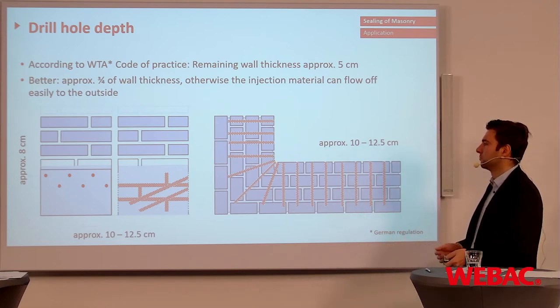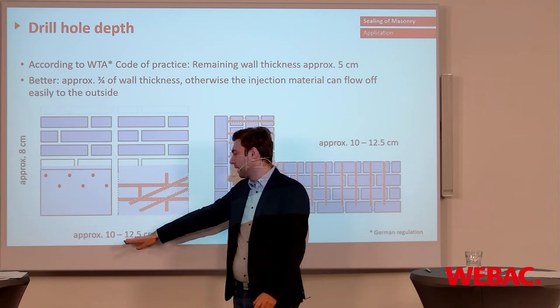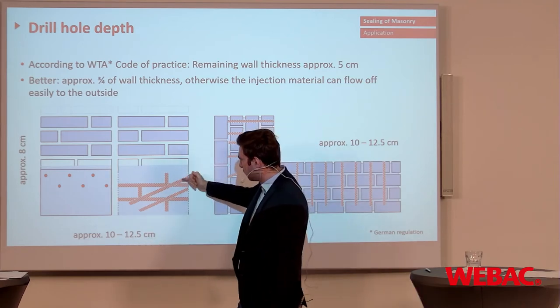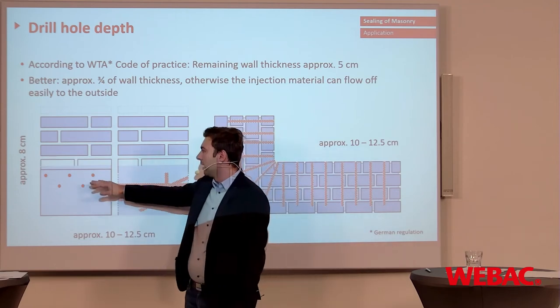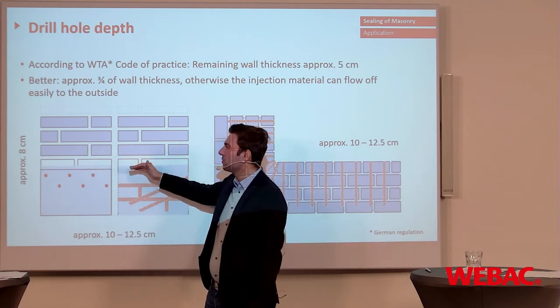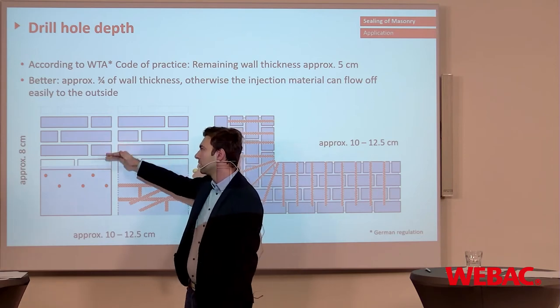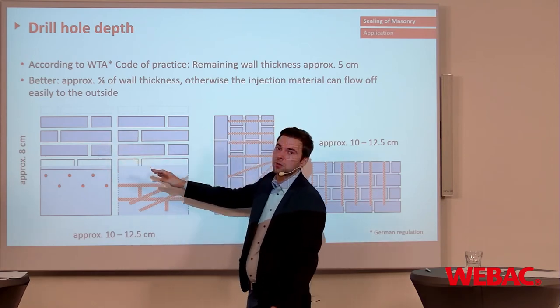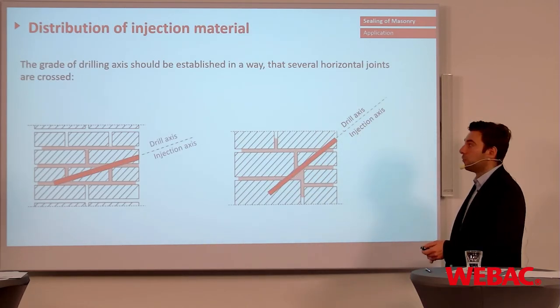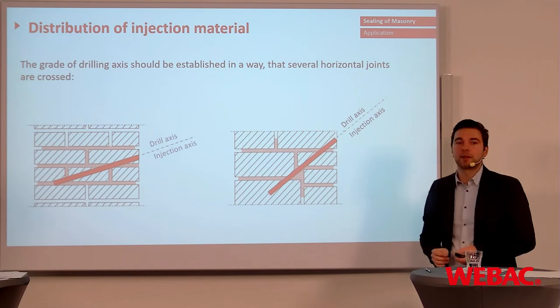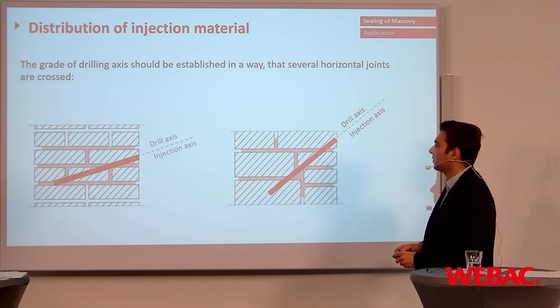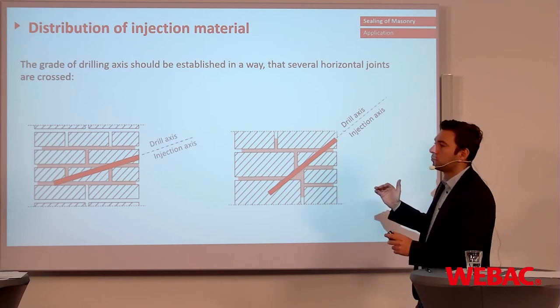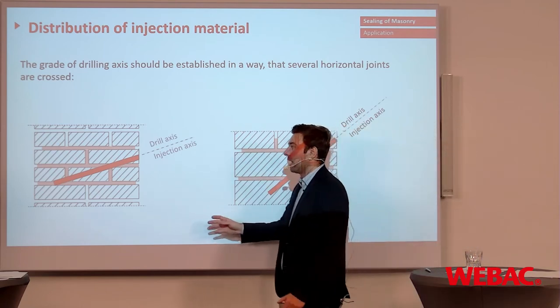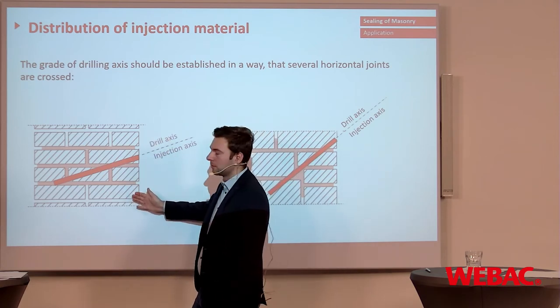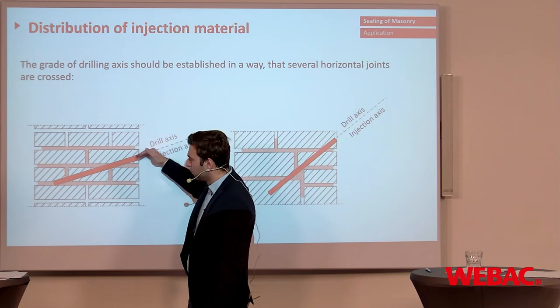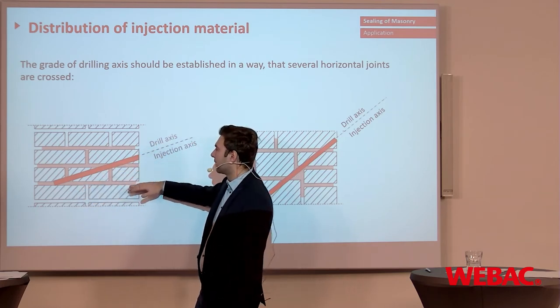through the construction. Once again, drilling depth 10 to 12 and a half centimeters. Try to hit at least two joints, and the distance depends on the type of masonry. If you have an even masonry, then it's usually 8 centimeters distance from one to the second row. For sure, it can be that you have to adapt your drilling angle. Normally, we are saying that the drilling angle should be approximately 45 degrees, and that's rather easy if you have an even masonry, because then you're pretty sure that you are going to hit at least two joints with these angles.